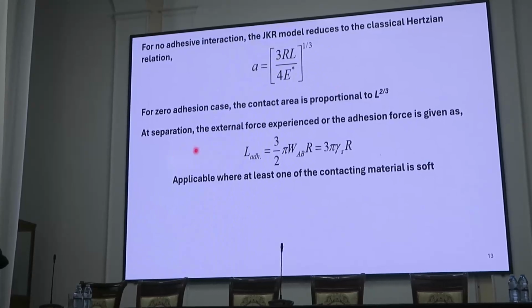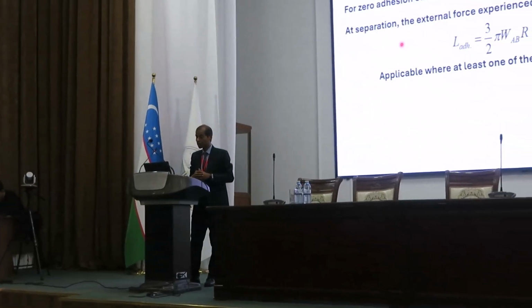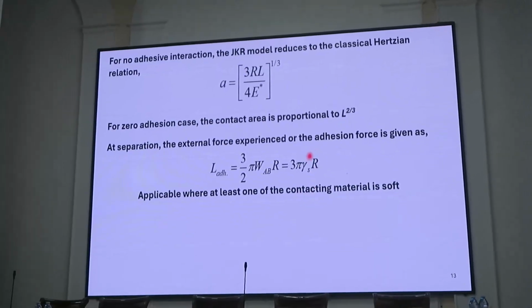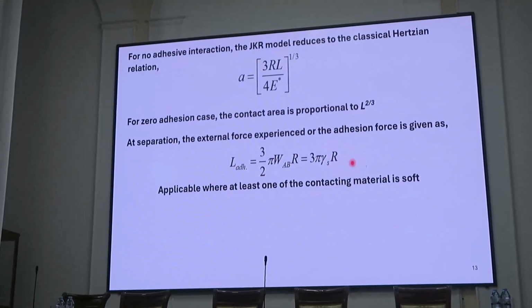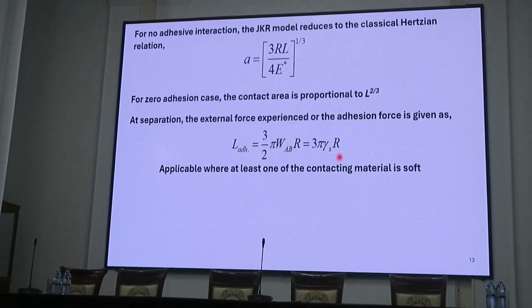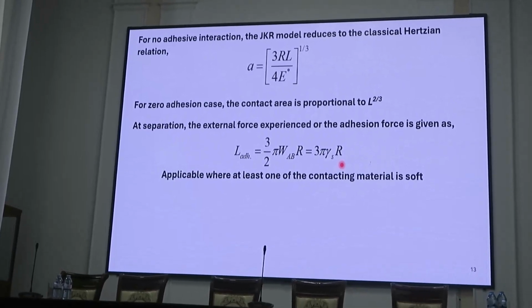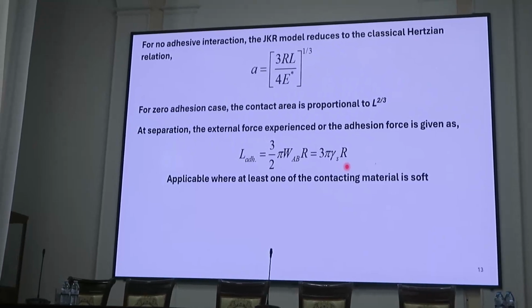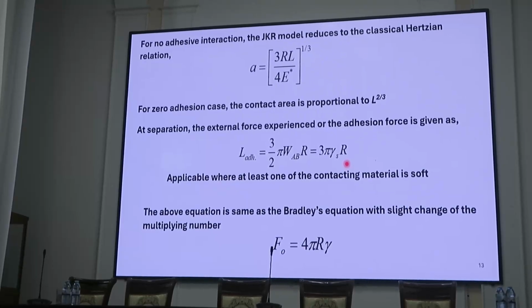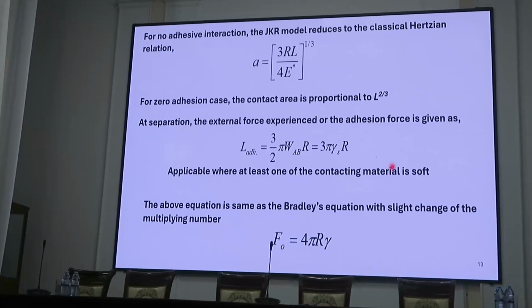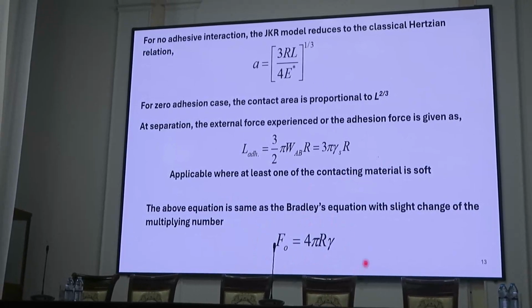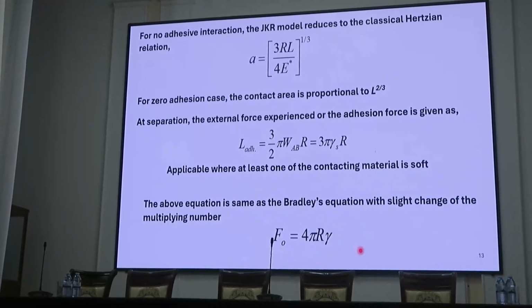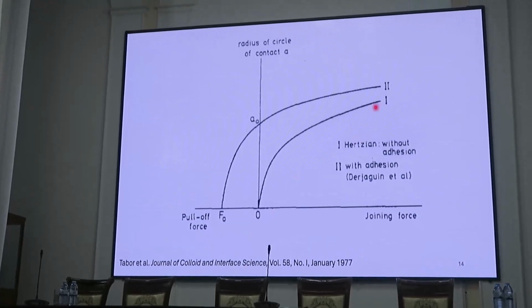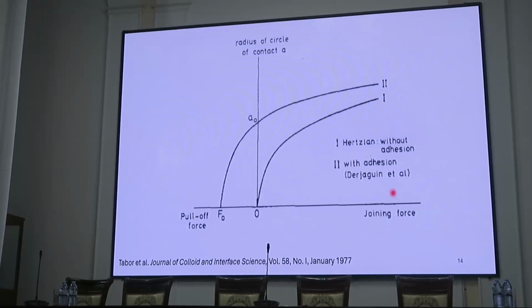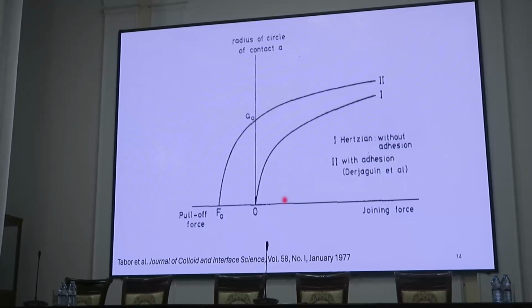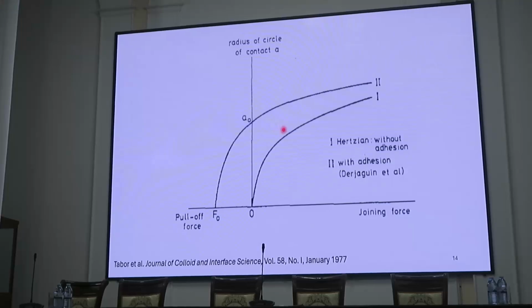Now at separation, when you are bringing the two surfaces apart, the external force experienced, or the adhesion force, will be given by this one. Here R is the geometry, the radius, and gamma is the interfacial surface energy. So surface energy plays a very, very important role in adhesion. When we are talking about boundary lubrication, where we have the possibility of dry contact, this adhesion will be an important part. This equation for the adhesion force is the same as Bradley's equation, which was given long back, which also relates to the surface energy. In terms of the graph, you can see when you are separating the two surfaces apart, say a ball on a flat plate, the joining force is reduced as the contact area is decreasing.